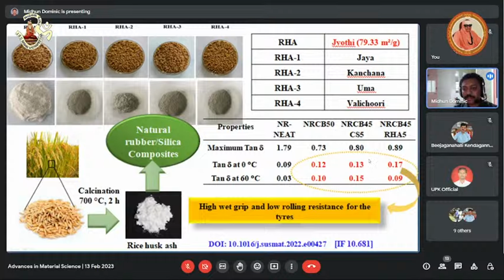We were surprised with the results because of tan delta at 60 degrees Celsius. Take NRCB45 with commercial silica 5. Normally, according to the literature, carbon black along with commercial silica is used for the development of green tires. Here 0.15 is the value, but we could obtain a tan delta value that decreases from 0.15 to 0.09. The lower the tan delta at 60 degrees Celsius, the lower the rolling resistance and the higher the fuel saving efficiency.